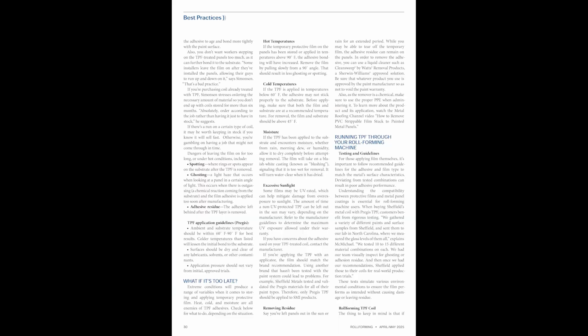Just-in-time application and removal. Because prolonged storage, exposure to sunlight, and outdoor conditions all pose risks, it's best to apply TPF as close to the installation date as possible and remove it promptly once the panels are put into place. You need to strip it off as you go when you're installing it, advises Sutherland. Delaying removal can cause the adhesive to age and bond more tightly with the paint surface. Also, you don't want workers stepping on the TPF-treated panels too much, as it can further bond it to the substrate. Some installers leave the film on after they've installed the panels, allowing their guys to run up and down on it, says Simonson. That's a bad practice.